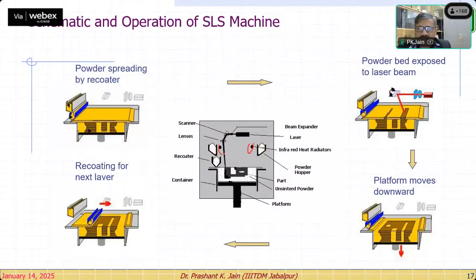So these infrared heaters, say for example, the sintering or you can say melting temperature is around 180 degrees centigrade for this polyamide nylon 12. So what happens? Just 4-5 degrees centigrade below, we heat the build platform, and the remaining 4-5 degrees centigrade temperature rise, which is required for sintering, not completely melting the polymer material, is achieved with the laser beam.